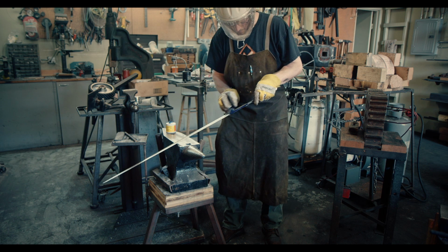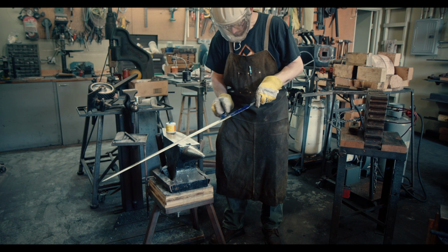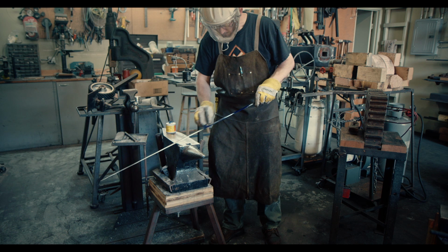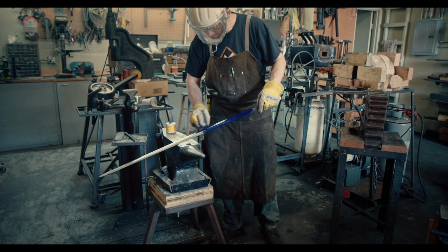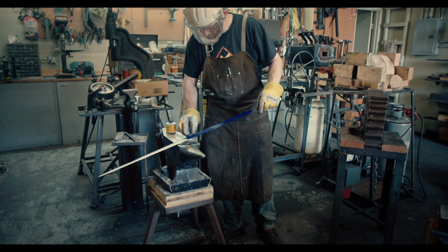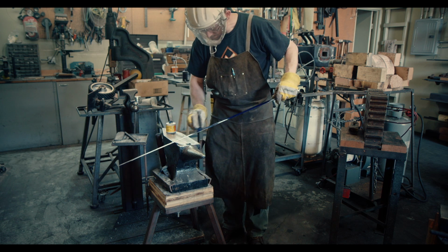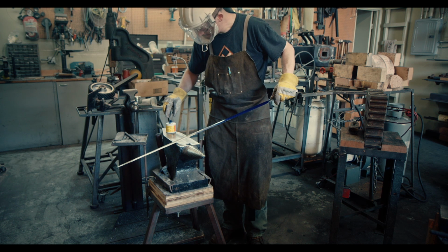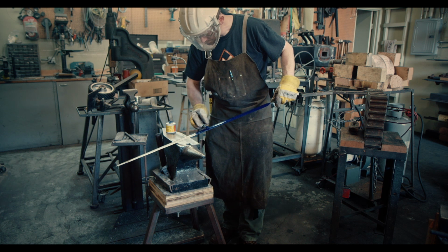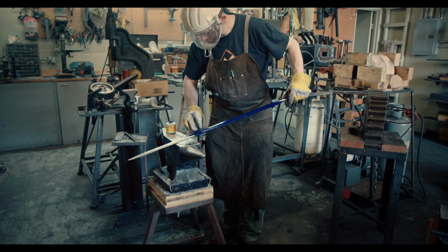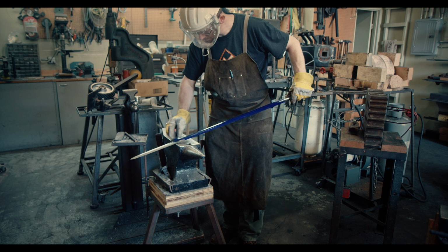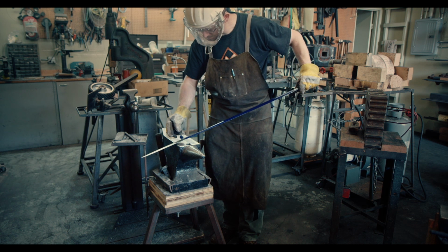For me at least, every step in creating a sword is iterative. With grinding, I switch between grinding the fuller and then grinding the edge. At first very aggressively, but then more carefully as I'm getting closer to the final shape. So, while you just saw me grind the fuller and the cutting edge, I'm not done yet. I need to do another light pass on the fuller, and thus it is back to layout fluid.